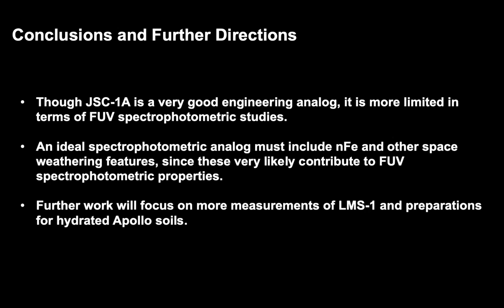And the further work after this will try to solve some of this by eliminating one possibility. And that is that, again, JSC1A is a low titanium dioxide content soil, whereas the Mare soils were a higher titanium dioxide content. So if we're comparing this to 10084, we need to eliminate the possibility that some of these differences are due to the titanium content.